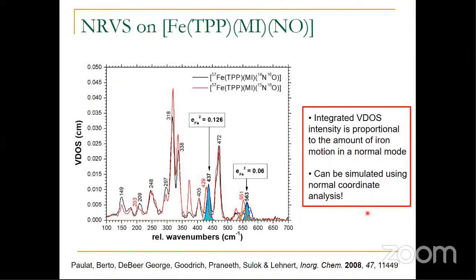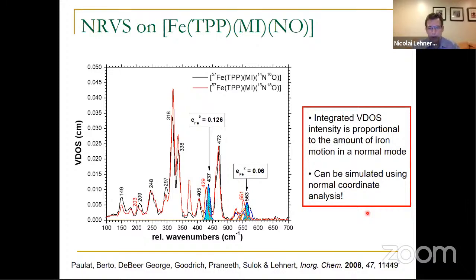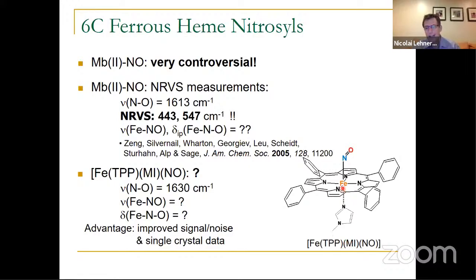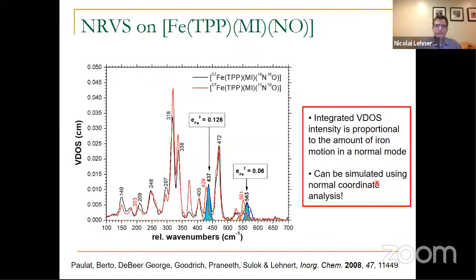And this is what the data look like. So here's an example of NRVS data for this model complex, right? This is this guy here: the iron tetraphenylporphyrin complex with 1-methylimidazole bound. It gives these kind of data here. Then we can prepare the complex with normal nitric oxide and with isotopically labeled nitric oxide. When you label with isotopes, so you make the mass higher, the vibrational frequency shifts lower, right? So we can label the NO and identify all the vibrations that have contributions from the NO ligand. You can see there are 2 modes that are isotope sensitive. One is at 563 wave numbers and one is at 443, right? So that confirms the data I mentioned before.